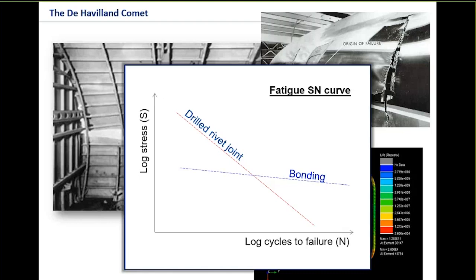Now, if you add to that a rivet joint as well, then what you end up with is a bit like the best of both worlds. The drilled rivet joint can cope with those high loads. But as we reduce the load, we see that it will still fail. That's because with the rivet joint, it's starting to initiate cracks, and those cracks grow until we get a failure.